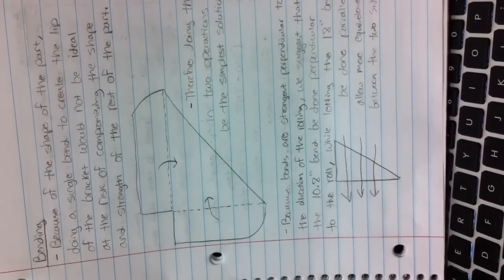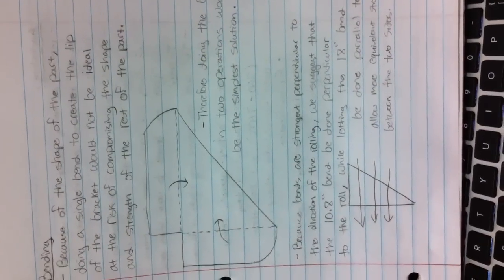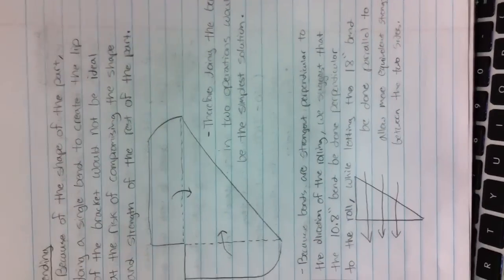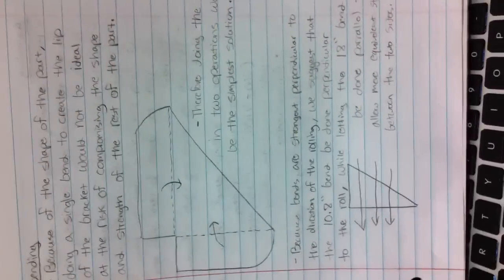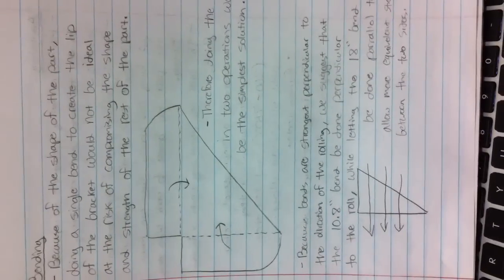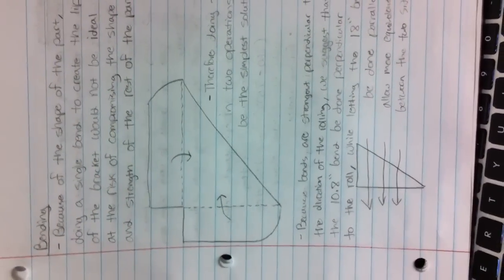As far as the direction of the bends with respect to the material, if we have the roll direction going this way, the strongest bend will always be perpendicular to the roll direction. Therefore, we said that the 10.8 inch long bend, the shortest bend, should be done perpendicular. Then the longest bend should be done parallel, which would be the weaker bend. We just said this to have the bend strengths be relatively equivalent, rather than having the short one with the weakest bend and the long one with the strongest.